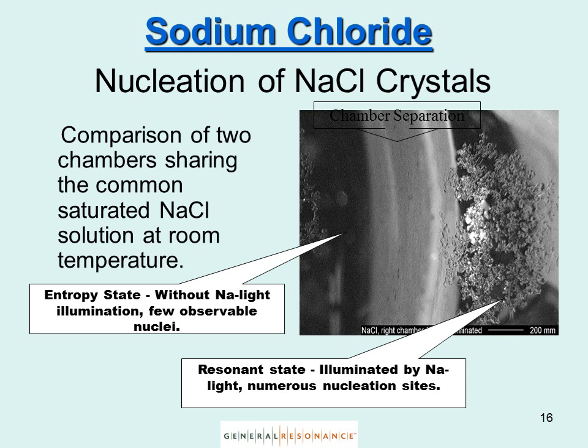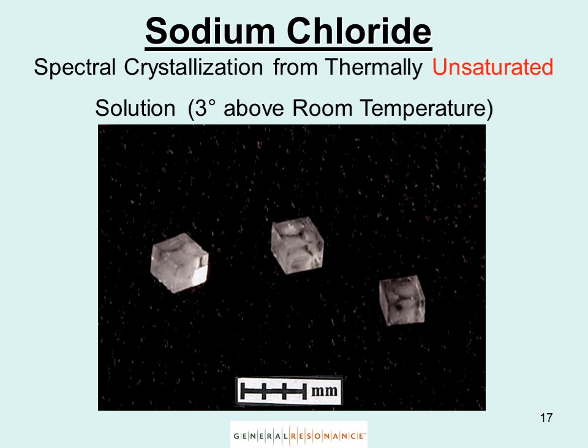So we said, can we change water? And here's the sodium chloride solution, and we did the crystal growth of sodium chloride. It's a long study which will be presented in a month at the Materials Research Society. On the left you see there's a septum in between. On the left, with no illumination, you get barely any nuclei forming. On the right hand side, exactly the same conditions but illuminated with sodium D line. That's 589. Now look at the funny thing.